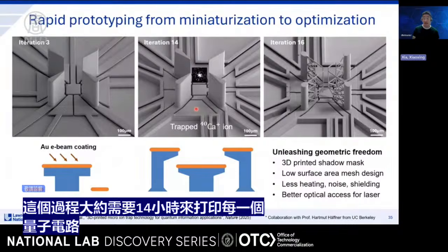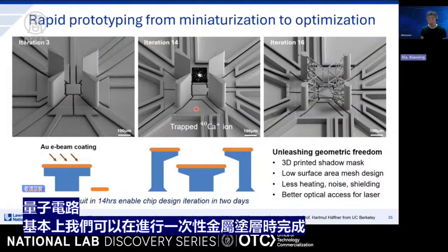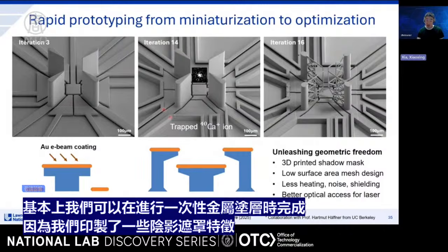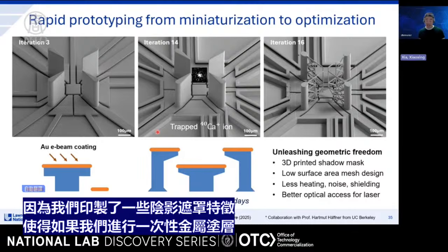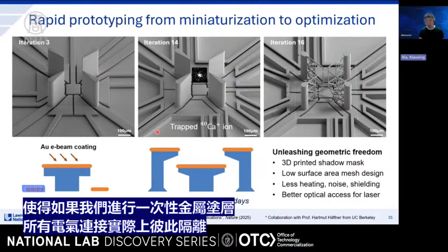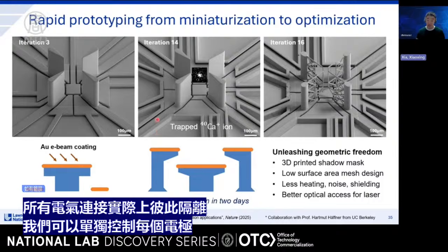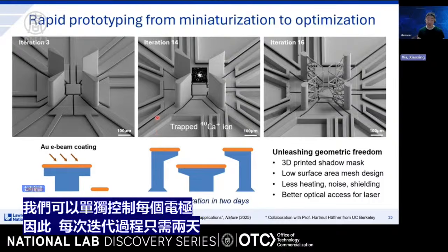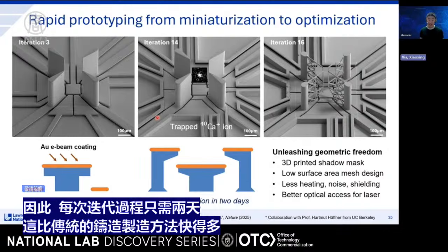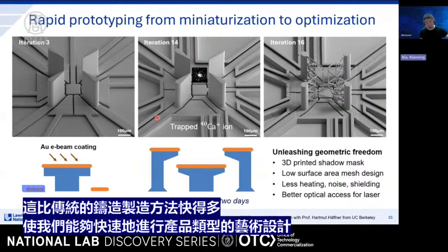And we can finish with one-step metal coating because we have printed some shadow masking features such that if we do one-step metal coating, all the electrical connections are actually isolated from each other, and we can address the electrodes individually. So each iteration process only takes 2 days. This is drastically faster than traditional foundry fabrication methods, which enables us to really rapidly prototype our designs.